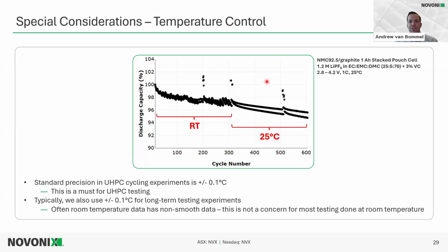So for our standard precision long-term testing, room temperature can be fine. If you want smoother data, use a temperature chamber. And then for UHPC testing, because we're looking at the difference between discharge and charge capacities, there can be no variation from one cycle to the next. We need very high precision and accuracy, mostly precision, to match the high precision and accuracy of the UHPC cyclers. So we put those in temperature chambers that are controlled to plus or minus 0.1 degrees.